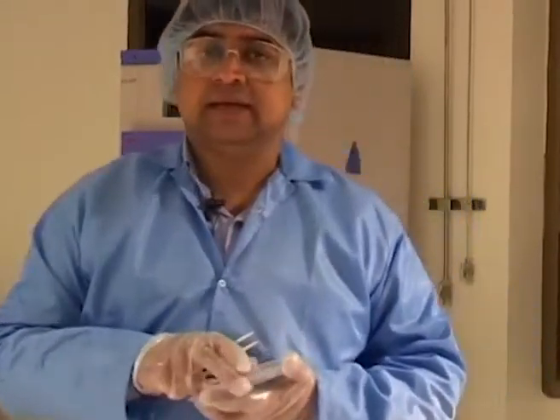There is a certain time for development which the resist manufacturer specifies, and this again is a function of the thickness of the particular resist. Our thicknesses are in the range of 20 to 25 microns, so the resist maker specifies the developing time for this particular thickness, which is about 4 to 5 minutes in our case. So let us try to develop it. Another important point that I would like to mention is that the resist which is left over on the surface while this developing is taking place, and is unexposed, turns white or cloudy as you spray isopropanol.